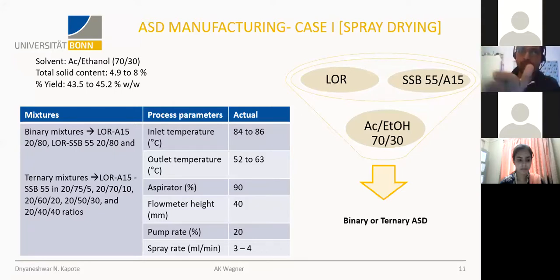And we did some solvent screening, where we found out that acetone and ethanol in the ratio of 70-30 helps to achieve a homogeneous solution. So we used this solvent, and the solid content which I kept was 4.9 to 8%, and the yield was 43 to 45%. The set inlet temperature was 84 to 86, and the outlet temperature was 52 to 63, and the aspirator was set at 90%, and the spray rate was 3 to 4 milliliter. So by that way, we obtained a binary and a ternary ASD.